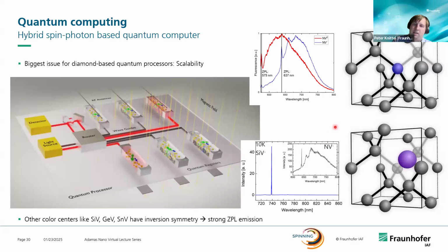On the other hand, in most cases, it's easier to do this with other color centers, like inversion color centers, as they have a very strong zero phonon line emission. So this makes it easier to actually get the photons indistinguishable. And this is also an approach that is mainly used in our project, but you lose this room temperature operation in that case, because these inversion color centers only have high coherence times if you go to cryo temperatures. We're still higher than what you use in the IBM system, for example.